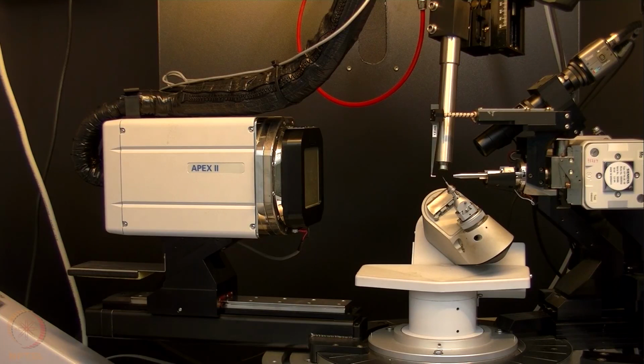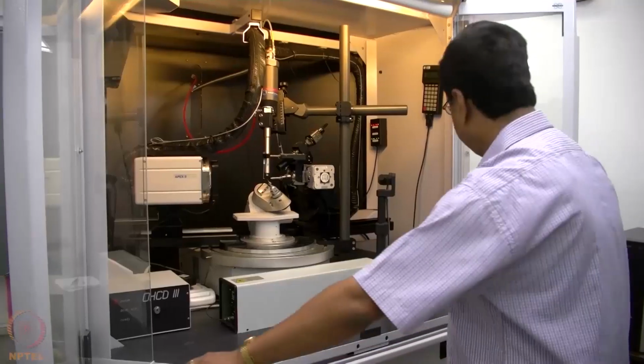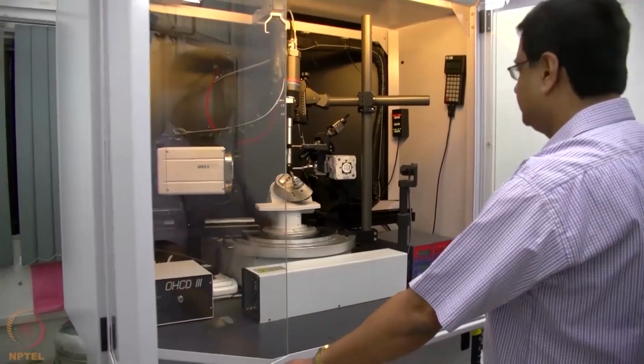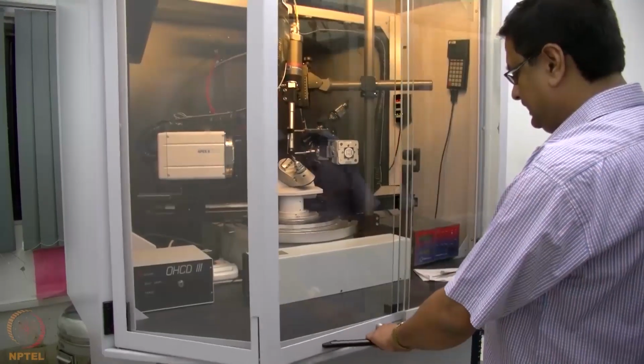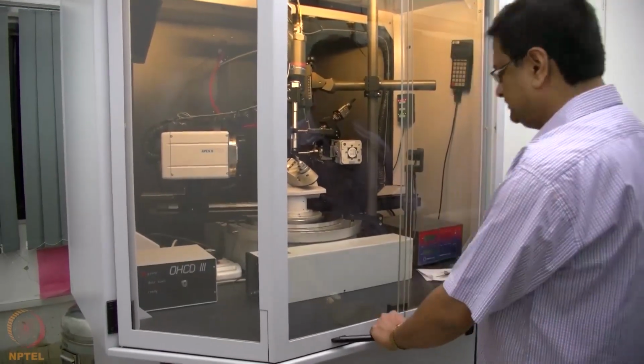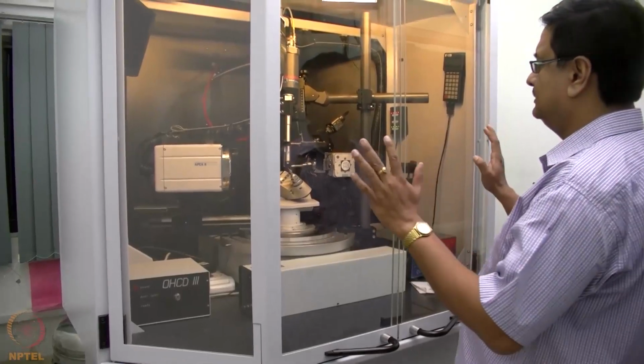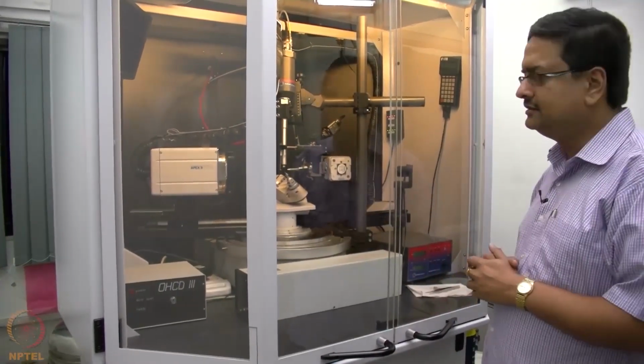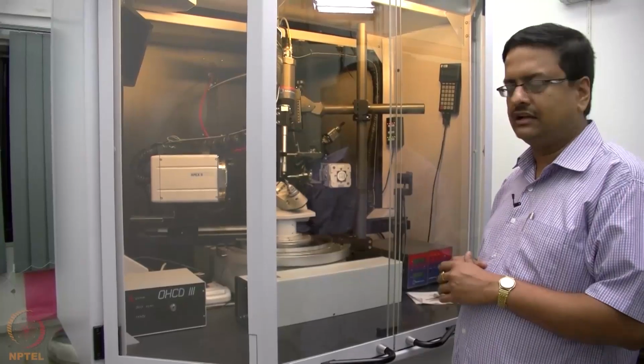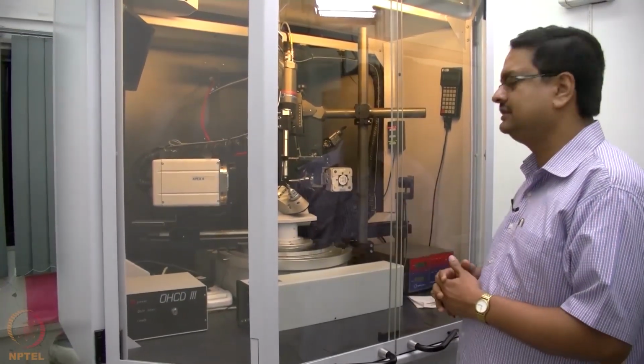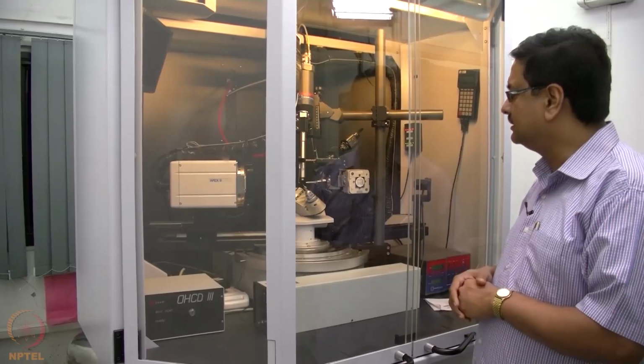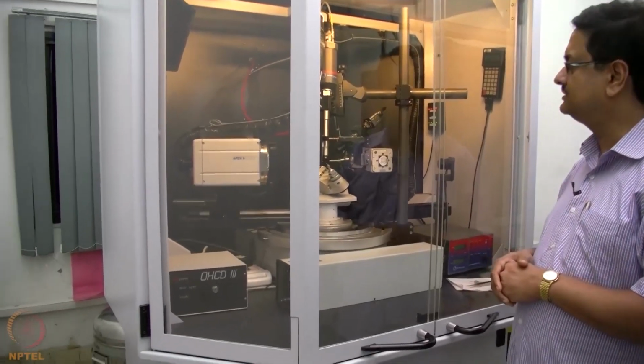So once we have completed the centering of the crystal, we should close the door and then start recording the initial frames to get the unit cell indexed. So this door needs to be closed from both sides. We bring it in the middle and then lock it like this. So now it is locked. So now one can switch on the X-ray inside the chamber. You can turn on, open the shutter and let the X-ray beam come, and we would get diffraction from the crystal that we have mounted.